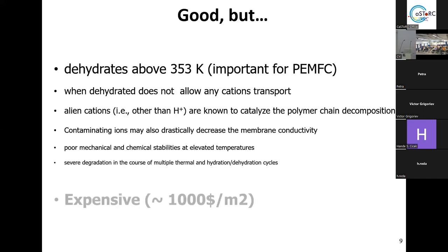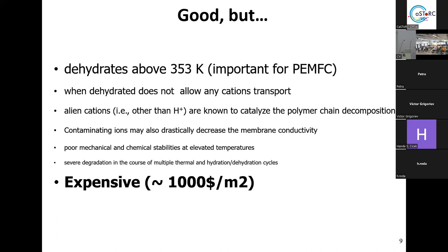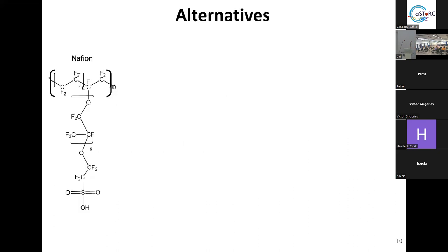So far so good, but there are many problems. If you want to use a fuel cell or battery at high temperature — which is generally desirable to prevent poisoning of expensive platinum catalytic surfaces — water disappears upon temperature increase, and without water there is no conductivity. Nafion dehydrates above about 353 K, and it is also very expensive, so people are looking for alternatives.